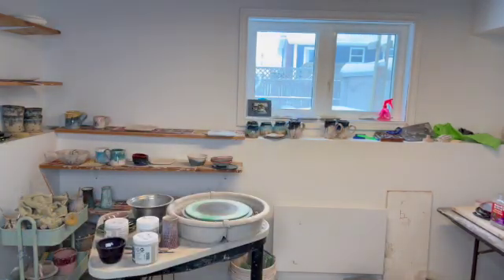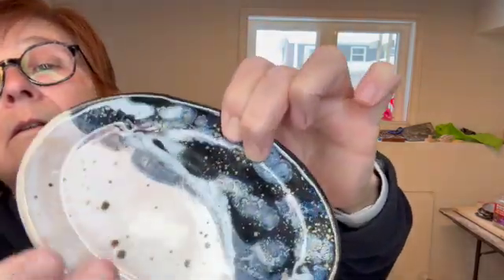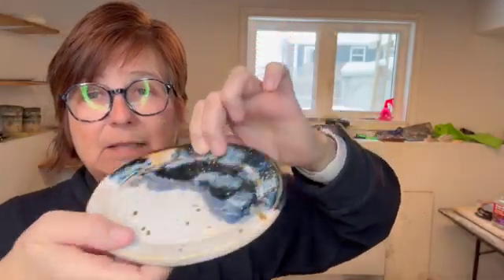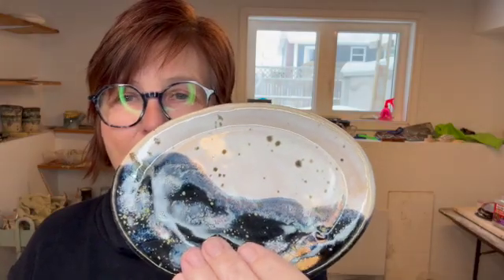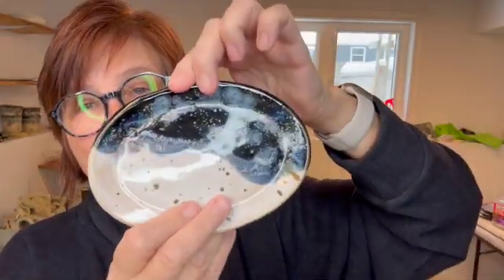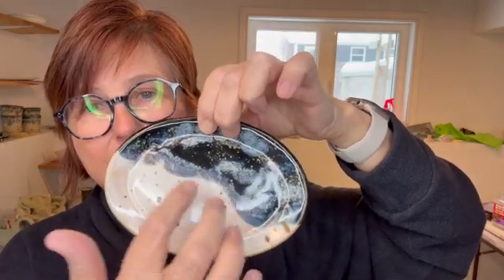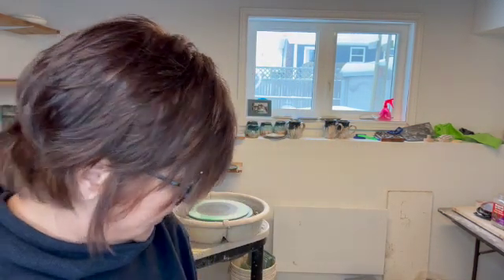And then the last thing I have to show you, oh, actually, no, another decal form, but it crawled a bit, so I have to refire it right there. I just went too thick on the glaze. So this I did a pour in my Studio Black, and then I did 2 coats of Honey Flux and 1 coat of River Birch below that, just letting them overlap slightly. Then I did Blue Hydrangea over all of that with some blobs of Light Flux, and the thought is Gold Moon, Fox, Stars, etc. So hopefully I can get those going, because I'll be sad if I cannot fix my issue with my Fox decals, because I've sold a lot of them.